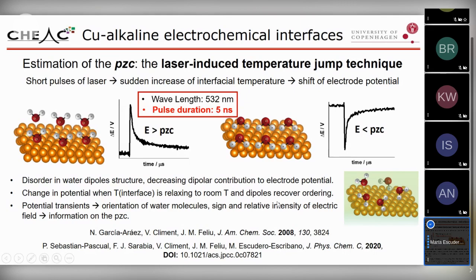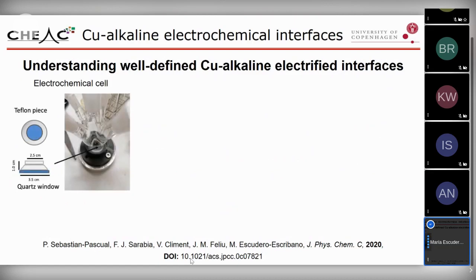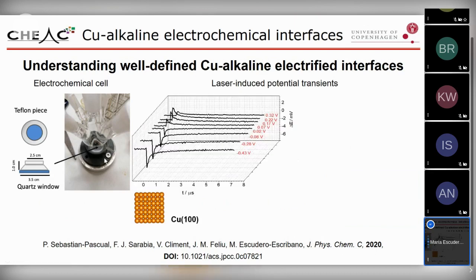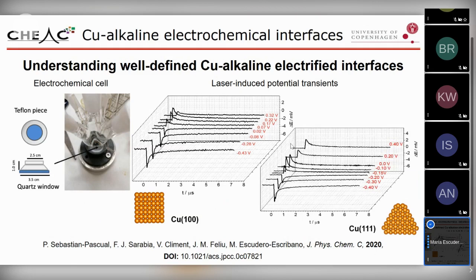And then these potential transients that are measured give information on the orientation of the solvent molecules, the sign, and the relative intensity of the electric field. So this is going to give us information on the potential of zero charge. And in summary, this is something that Paula did using an electrochemical cell in which, in order to work in these conditions, the electrolyte was confined in this space in the Teflon piece that they designed. And then they applied these transients for both copper 100 and copper 111.